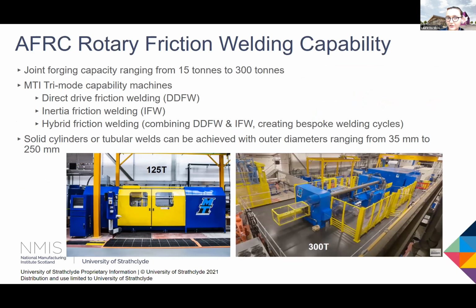In terms of the AFRC's rotary friction welding capability, we have two machines that have a joint forging capacity ranging from 15 tons to 300 tons. We have MTI's tri-mode capability machines. By tri-mode, I mean that we're able to do direct drive friction welding, inertia friction welding, and hybrid friction welding, which is a combination of the two weld cycles. We're able to weld solid cylinders or tubular welds with outer diameters ranging from 35 millimeters to 250 millimeters, but essentially we're able to weld anything that's axisymmetric.